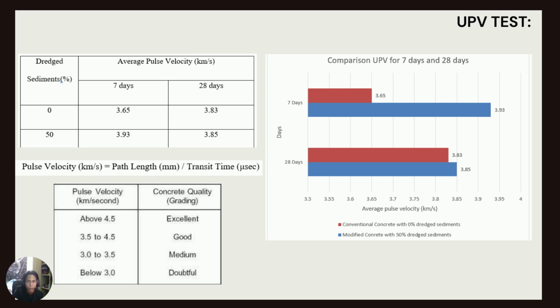Next, for the UPV test, the table below shows the concrete quality based on the pulse velocity obtained. 50% dredged sediments replacement gives higher pulse velocity for 7 and 28 days compared to the conventional concrete. Based on the overall results, 50% dredged sediments have a higher pulse velocity than conventional concrete. This means that the higher the pulse velocity, the better the concrete quality. This is due to the dredged sediment's smooth and rounded surface texture as a result of the weathering effect. The particles are intact in the concrete, thus filling up all the gaps and leaving very little space. As a result, the velocity was higher when compared to the conventional concrete.